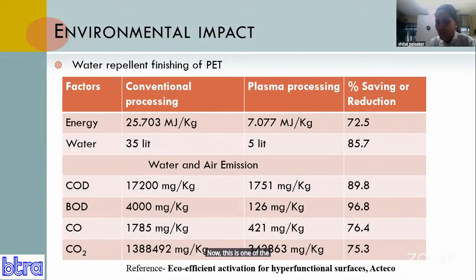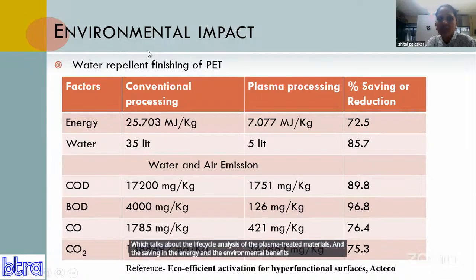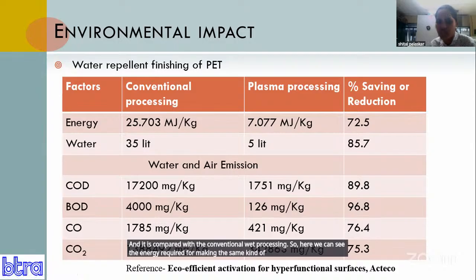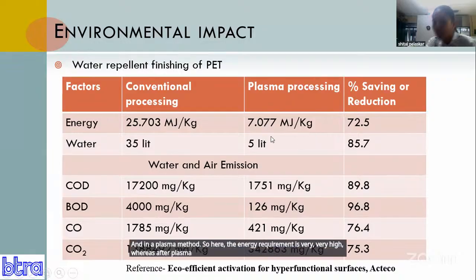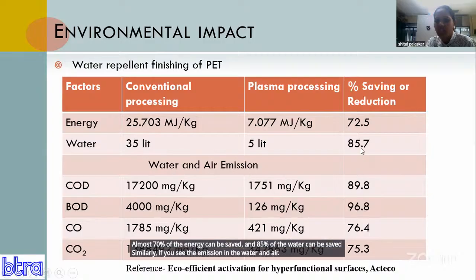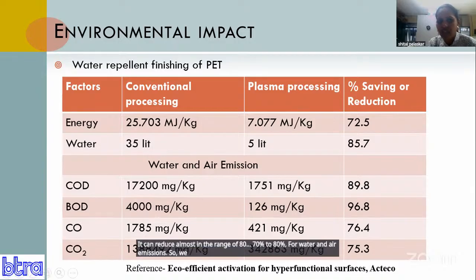Now, this is one of the case studies I have taken from the published literature, which talks about the life cycle analysis of the plasma treated materials and the savings in energy and the environmental benefits. This study is done for the hydrophobic finishing of polyester fabric, and it is compared with conventional wet processing. Here we can see the energy required for making the same kind of hydrophobic finishing in a conventional method and in a plasma method. The energy requirement is very, very high for the conventional method, whereas if you do the same finishing using plasma treatment, almost 70% of the energy can be saved and 85% of the water can be saved. Similarly, if you see the emissions in water and air, it can reduce them by almost 70 to 80%. So we can say that plasma is a very environmentally friendly technology.